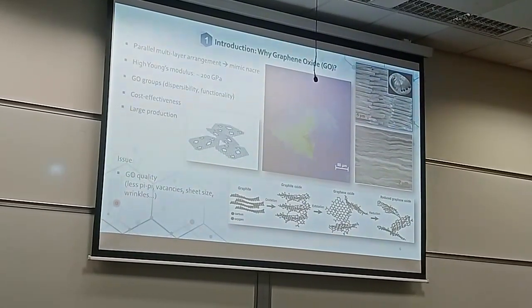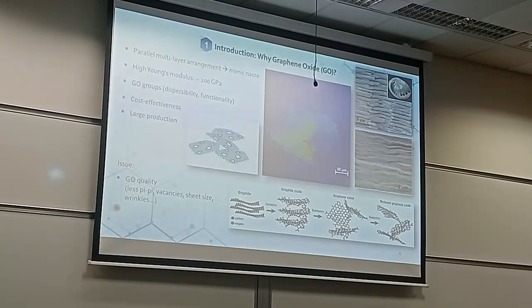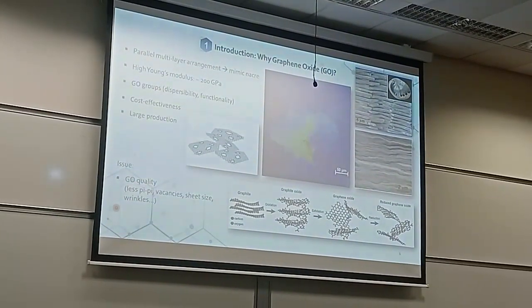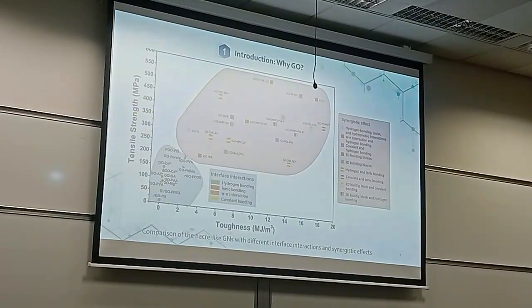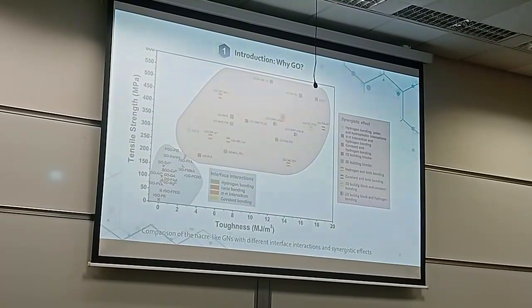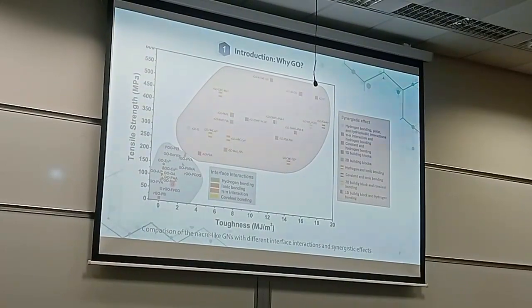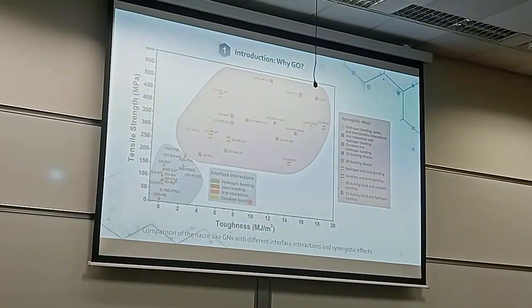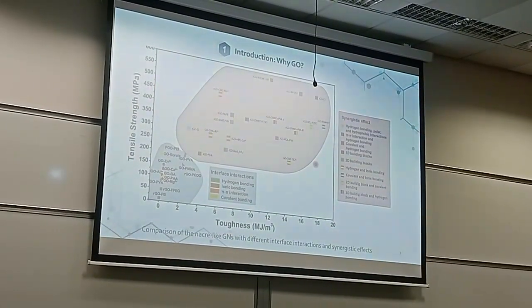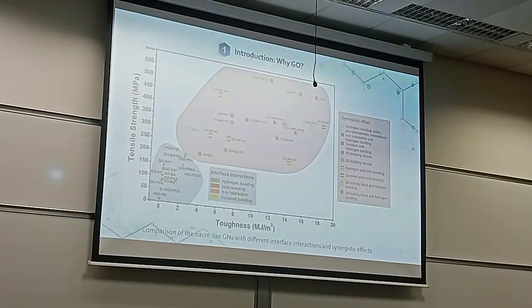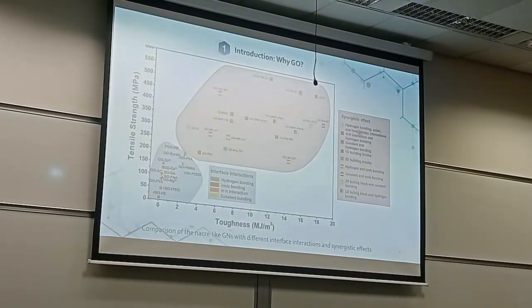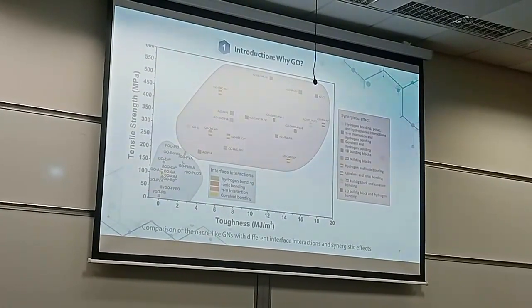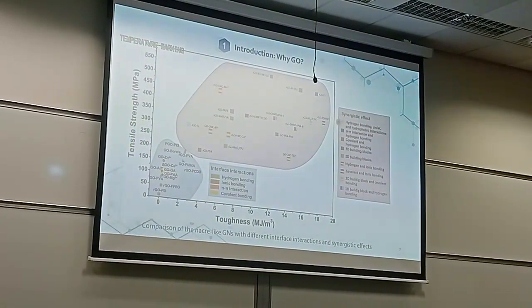So all of this affects the graphene oxide, and unfortunately there is not only one graphene oxide. It may also depend on the oxygen groups, like the C/O ratio, on the sheet size, on many parameters. There are many works trying to make graphene oxide Nacre-like composites, either with some polymers or by adding interface interactions using some ions or hydrogen bonds, etc. And then in recent works, they try to get other synergistic effects using maybe 2D materials, 1D materials with other polymers or similar ionic interactions. You can find this graphic in one video. I can also share it later.